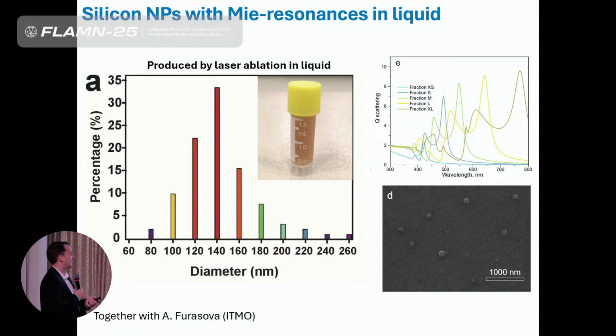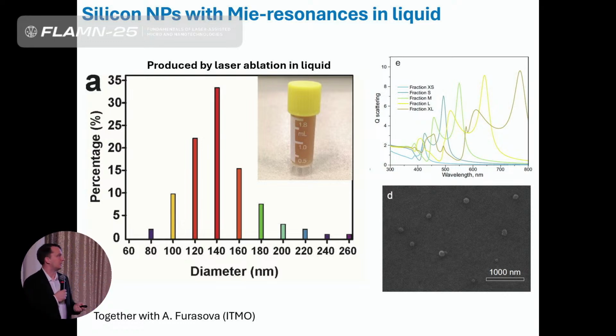And in our lab, we also used laser ablation to create such nanoparticles, but to create them in liquid. This is a very well-known technique, laser ablation in liquid. Here is an example of a bottle with a silicon suspension, a colloidal solution with nanoparticles of different size distribution, and after deposition on a surface we can have such a distribution of nanoparticles, and we can play with the concentration. Each nanoparticle has a scattering spectrum, as you can see here. There are some calculated values, and we also measured a lot. It means that we can cover the whole visible range. They scatter light in the whole visible and near-infrared range.